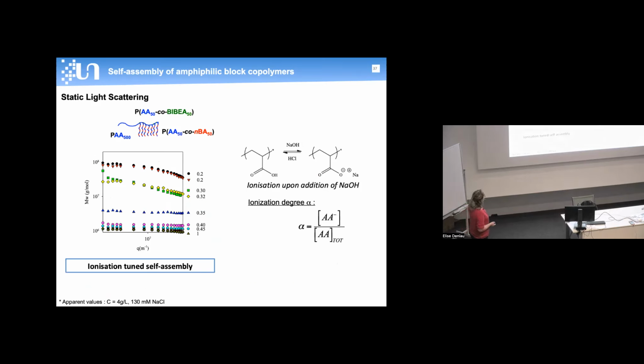So again, static light scattering helps us to study the aggregation behavior of such a copolymer by observing the influence of the molecular weight on the scattering wave vector. And here what you see is that when the ionization degree decreases, the molecular weight increases and the angle dependence becomes more important. So this means that there is an aggregation induced self-assembly of the bottlebrush copolymer with a critical value of alpha around 35%.